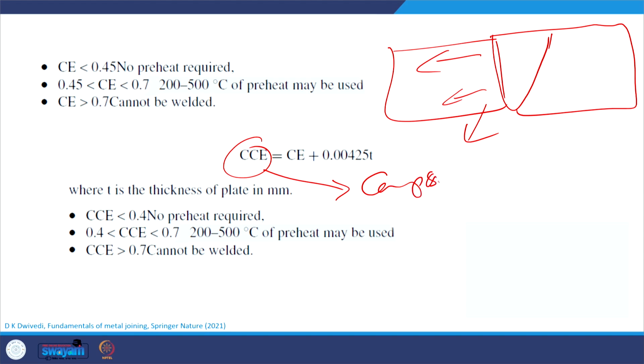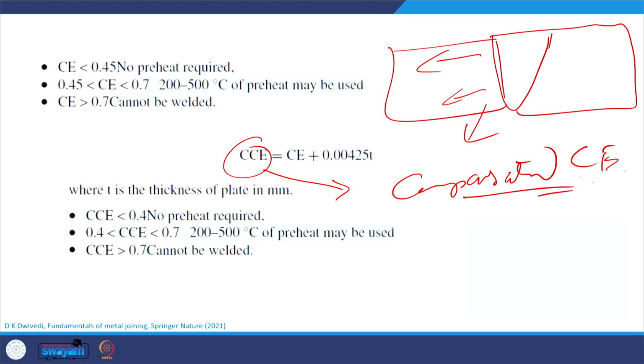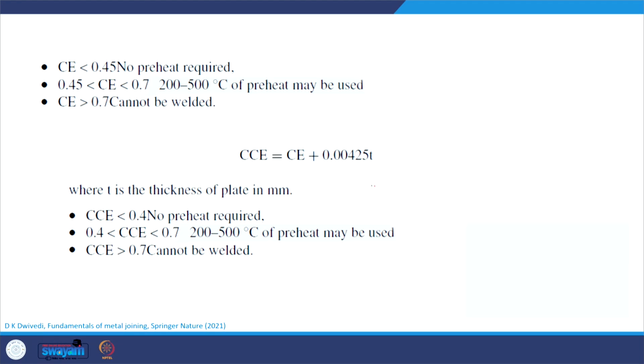compensated carbon equivalent. So, compensated carbon equivalent CCE is calculated using the carbon equivalent plus the thickness factor 0.00425t. T is the thickness of the plate in mm, and in that case the empirical equations are used for taking a call on the preheat requirements.